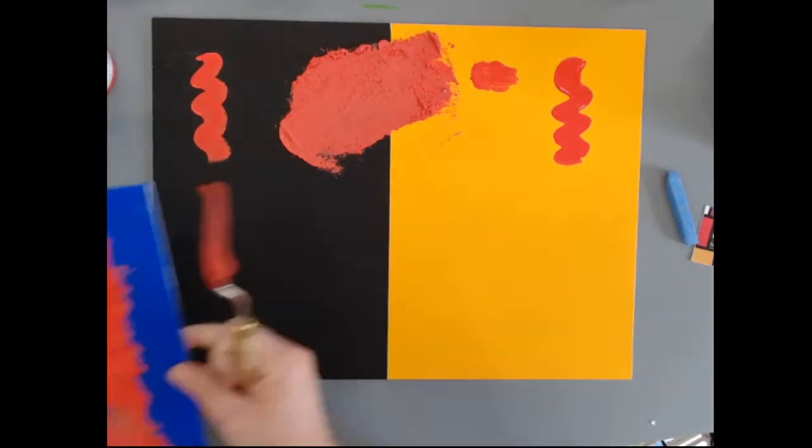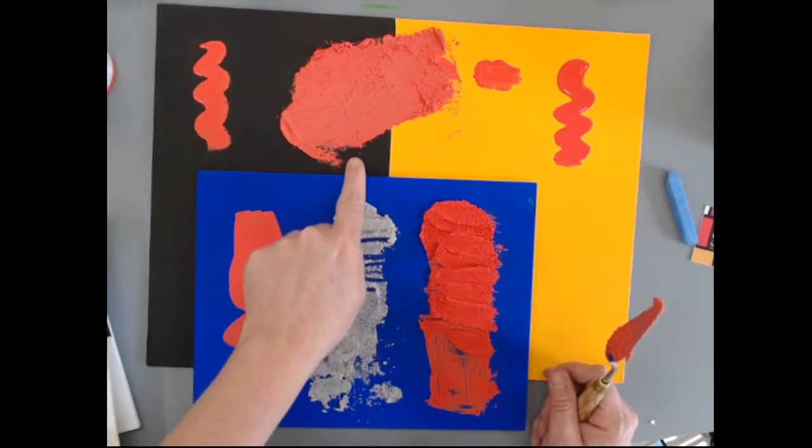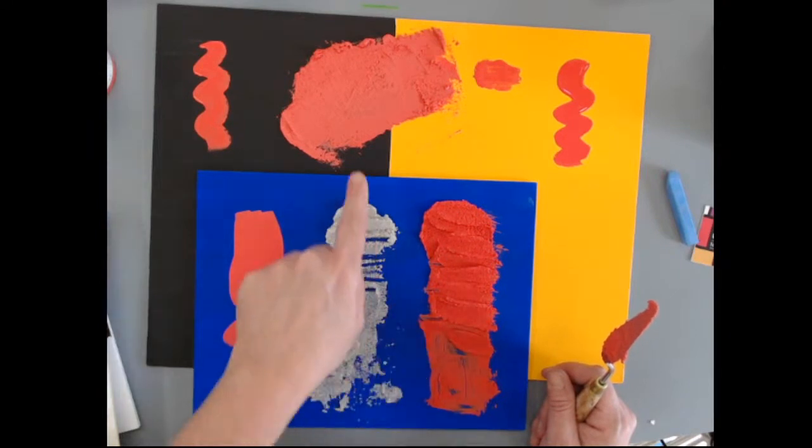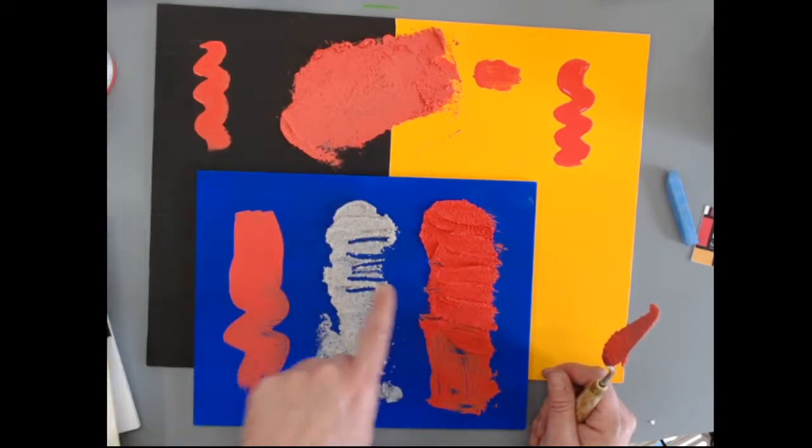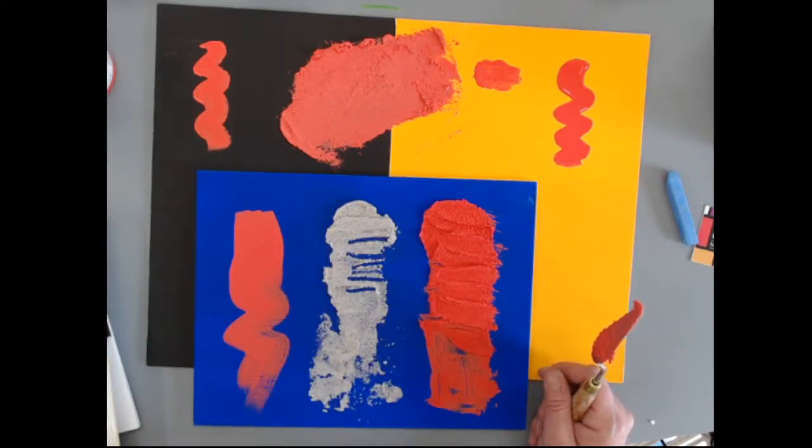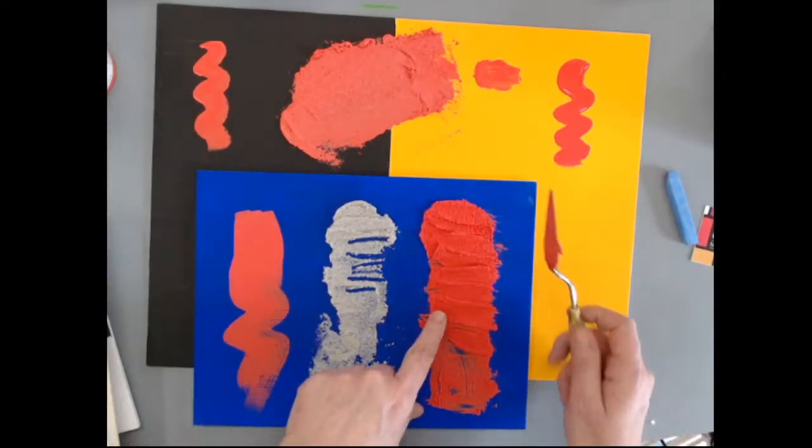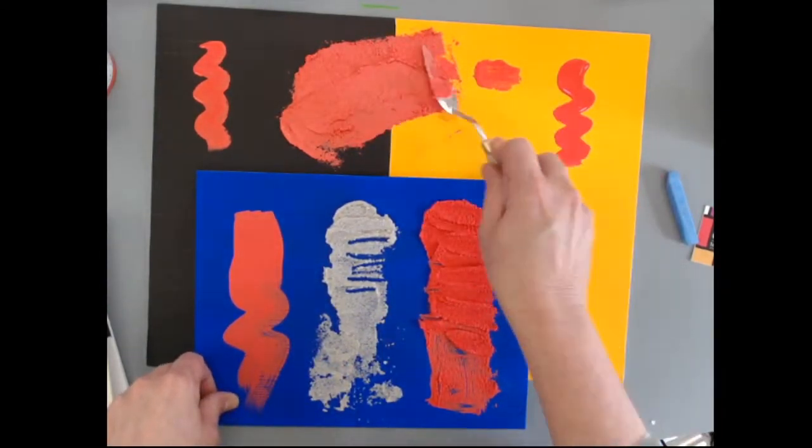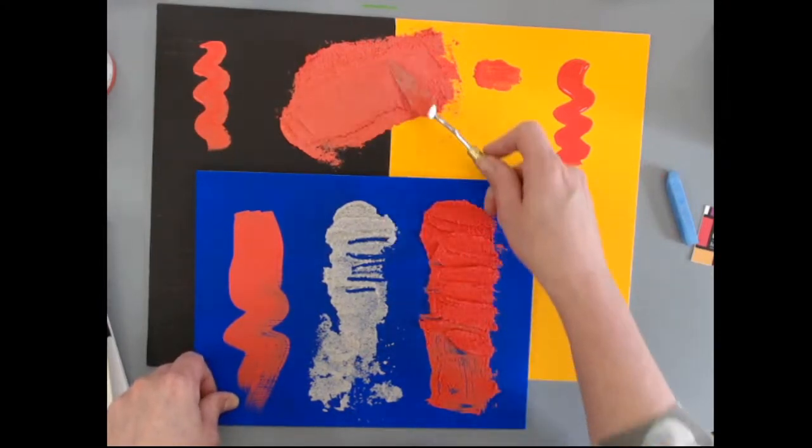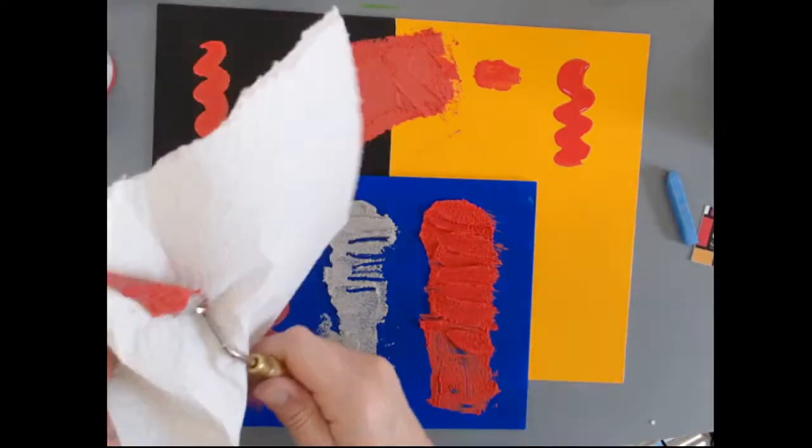So that will dry like this. Now, the reason I wanted to pull this out and do the mixture here is because the binder in this will clarify and your color will deepen. So just so you know, these colors are very similar here and here. There's not a big shift. So once this dries, it should be pretty similar to the actual paint that you've got out of the container if you use enough paint. So when I did this one, I want to say it was about 30 to 40% paint. Probably used a little less here. Still, it's going to deepen. Okay, terrific. Let me see if there's any questions before I move on to the next demo. Thank you to my team. You guys are terrific answering questions as we go.